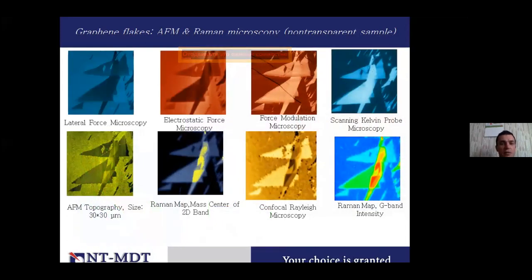And here is example of the complex study of the same area using AFM and Raman. So on the left top, you can see lateral force, which show us some friction properties on the graphene, then electrostatic force distribution, then force modulation. It is about mechanical properties, about elastic properties. Then it's a work function of the graphene flakes. Then it's a topography. Then it's a Raman map, mass center of 2D band shift. Then it's a Rayleigh microscopy and Raman map G-band intensity. So you can see that all these measurements can be done. Again, I would like to put your attention from the same area in the same time.